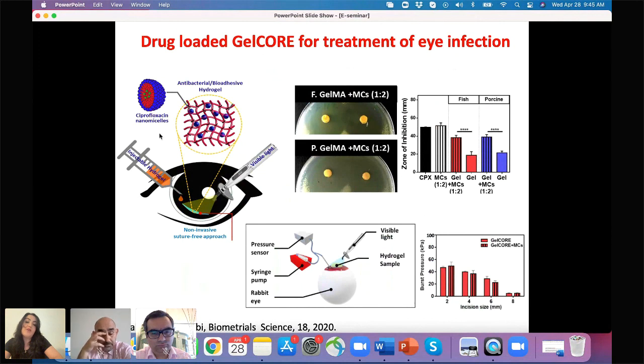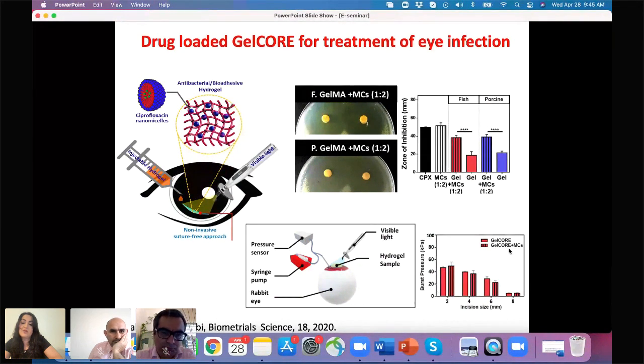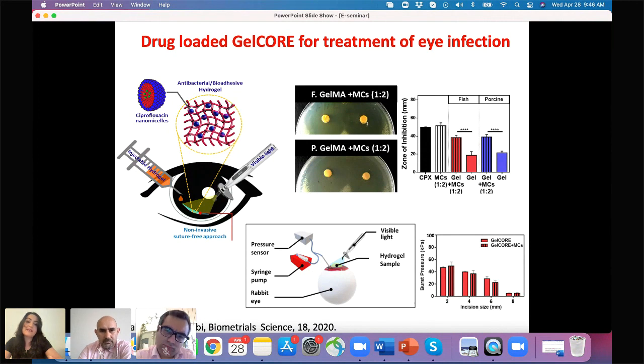And this time, we form micelles loaded with antibiotics. Once we create these micelles, they can be incorporated in the hydrogel to form these antimicrobial biomaterials. And then we show that as we incorporate these micelles loaded with antibiotics inside the gel, it's still effective to seal incision with different sizes on the cornea. So as you see here, for hydrogel with and without micelles, we have the same burst pressure for different incision sizes. So therefore, this platform can be used as a matrix for delivery of different drugs into the eye. And it can be used as a photocross-linkable hydrogel that can adhere on the surface of the eye, or it can be used as a pellet, which can be injected in the eye for controlled release of drug over time.